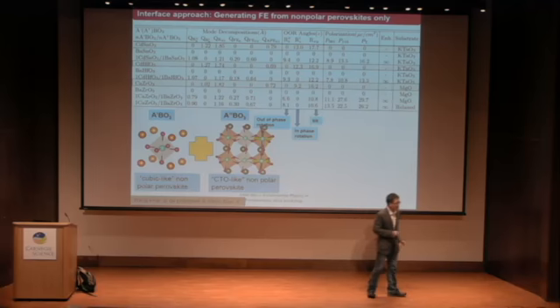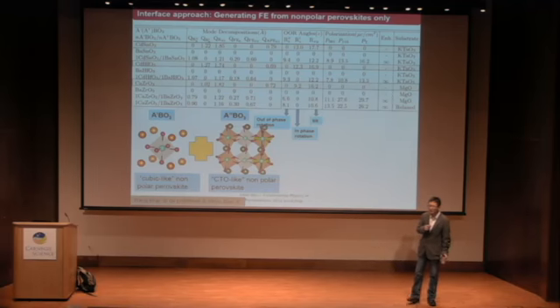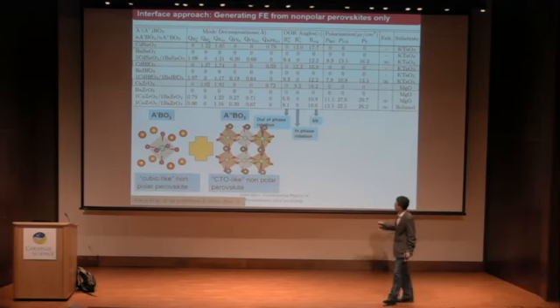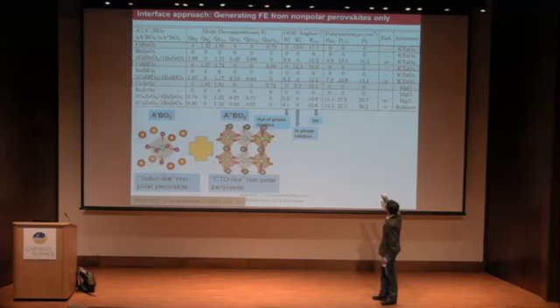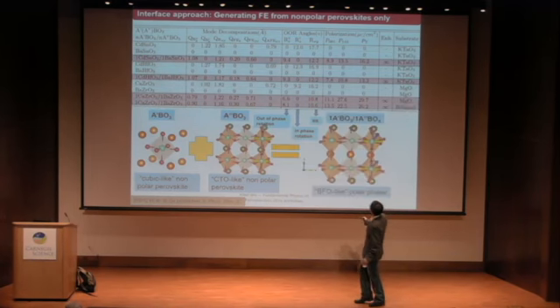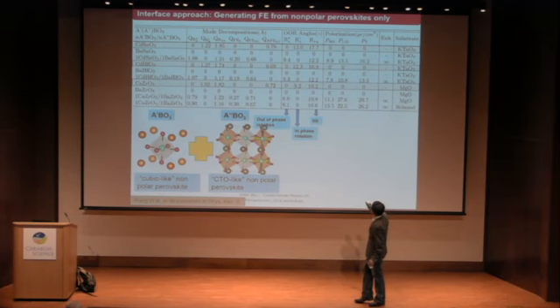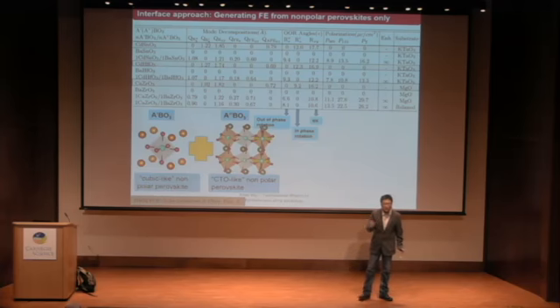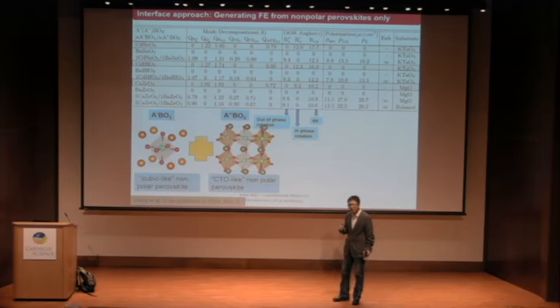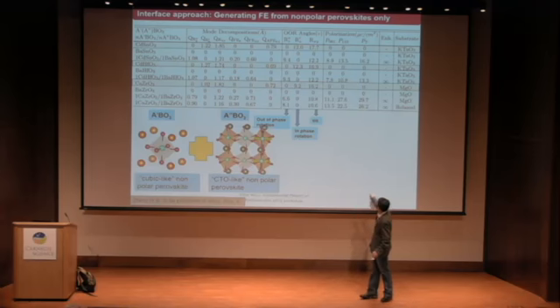In the second material, we select a highly CTO-like structure in which the tilt is pretty huge, along with rotation. Because the in-phase rotation and tilt develop an antipolar state, this suppresses ferroelectricity. So there's no ferroelectricity in any direction.